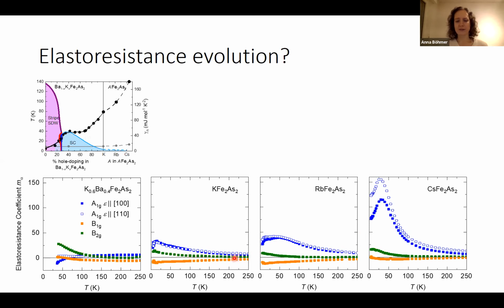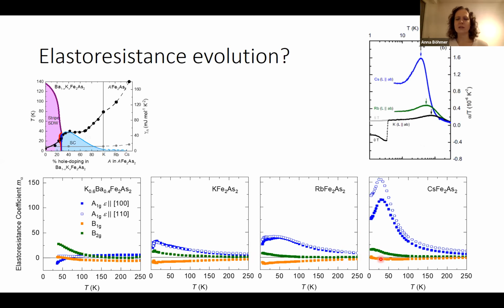And the B1G is finite as well, but does not diverge. There's no Curie-Weiss or power law dependence here. So the A1G component compares very well to our Grüneisen ratios, or even the temperature dependent thermal expansivity here. And there's a fundamental reason for that. It is that the resistance in these compounds is strongly dominated by the entropy. And so with the elastoresistance, the A1G coefficient, we actually get a measure of the Grüneisen ratio here.